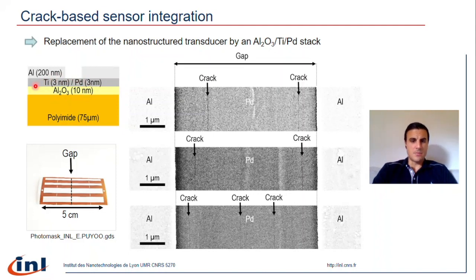deposition and E-beam evaporation. As you can see on this schematic, we have first grown a thin alumina layer by ALD at low temperature on a polyimide substrate. Then we have deposited our titanium palladium stack by E-beam evaporation at room temperature. And finally, we have patterned some aluminum top contact by a lift-off process from UV lithography.